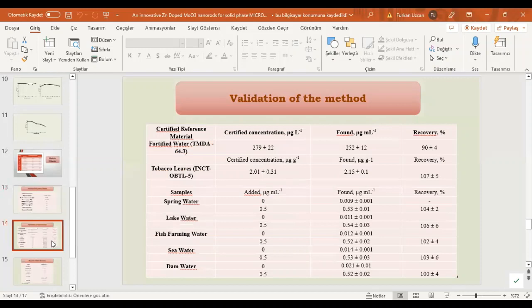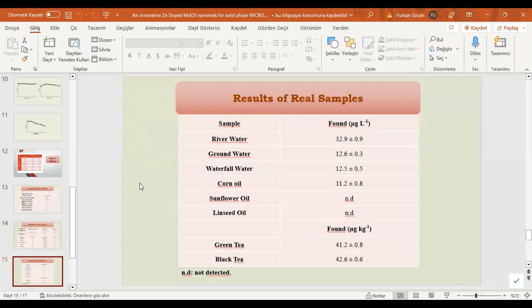For validation of the method, we used two certified reference materials. First one is fortified water sample and second one is tobacco leaves. As you see on the table, we got quantitative recovery. Also for validation of the method, we used water samples at two concentration levels. As you see on the table, the results are quantitative. Then after we validated our method, we applied it to some water samples, oil samples, and tea samples. You can see the results on the table.